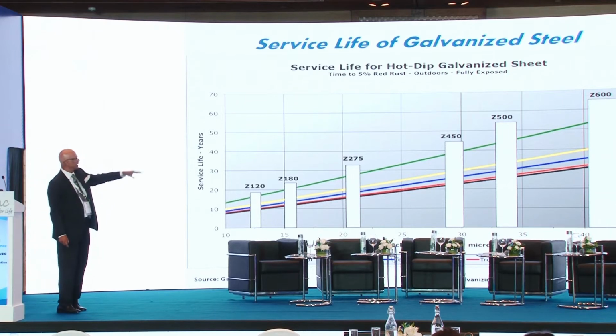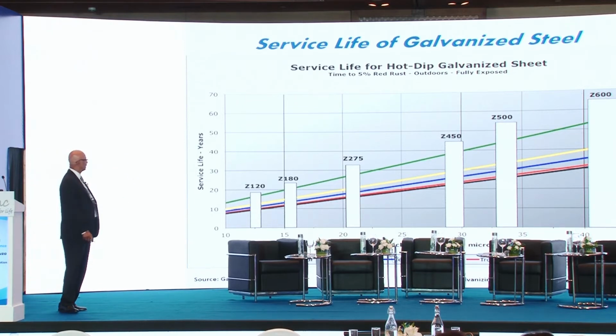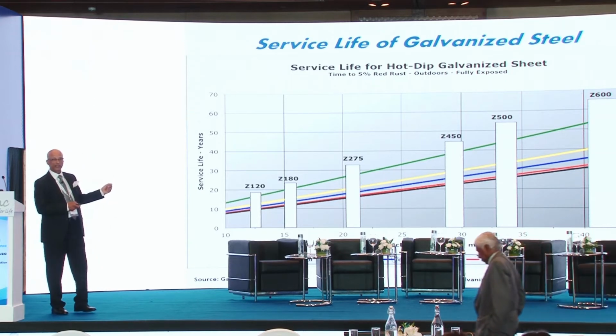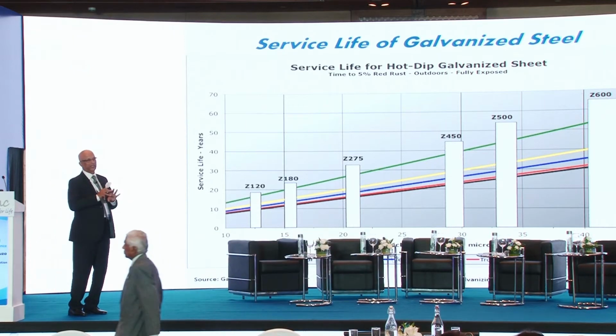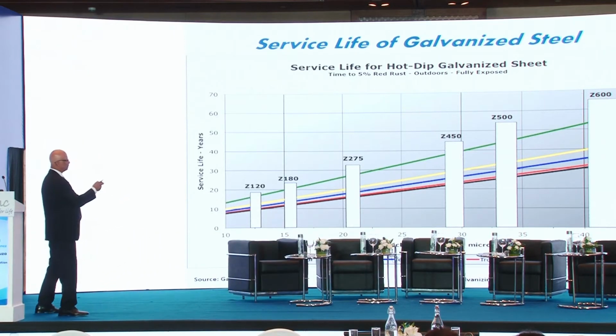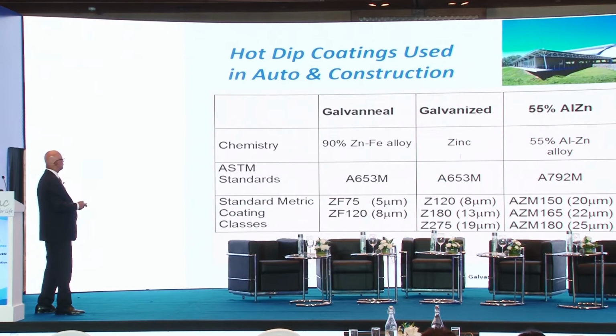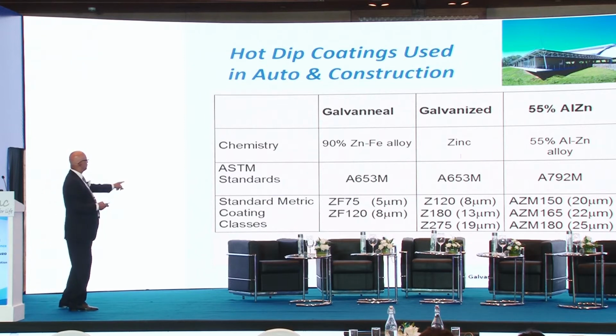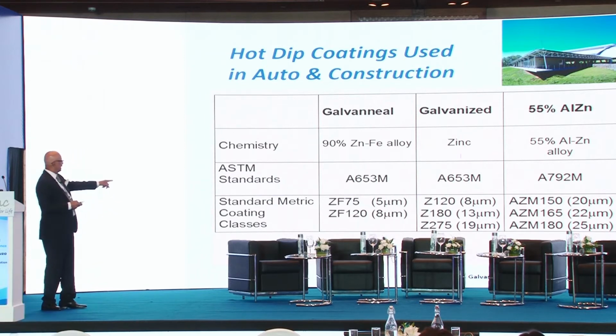So you can take that calculation to a Z600 coating. Again, these are not necessarily outdoor test measurements. These are limited tests, then extrapolated to deliver this type of service life expectation. Again, the only thing I want to talk about on this slide is the standard coating thicknesses at the bottom column: in the case of Galvanneal, 5 micron thick coatings, or 8 microns.